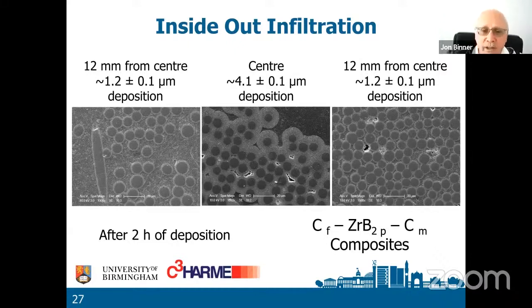And again, you can see here the inside-out infiltration. So you've got the center one there, and you've got about 4 microns of deposition. This is after just 2 hours of depositing. 12 millimeters from the center in either direction, and you've deposited about 1.2 microns of deposit. So again, nice clear evidence that we are getting our inverse temperature profile.